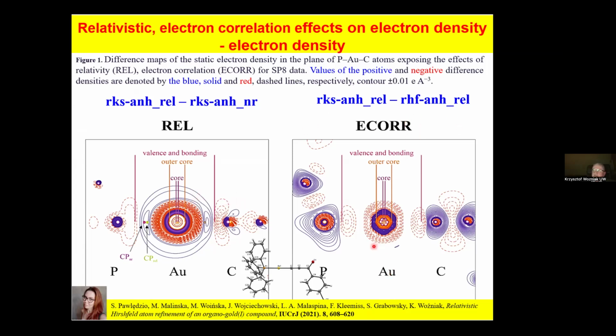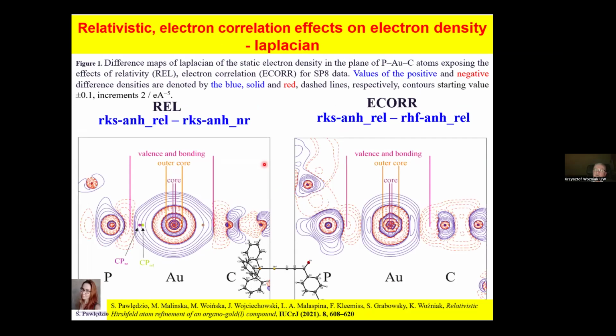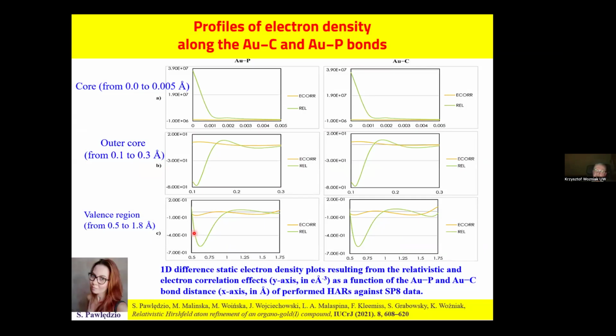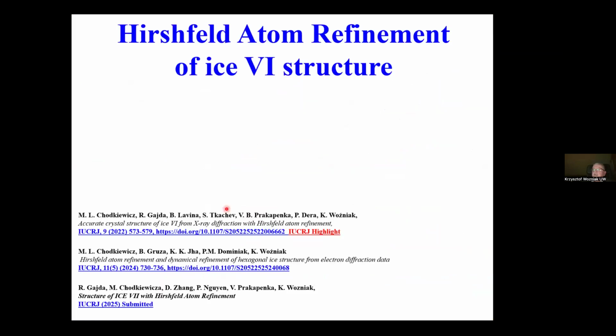In the case of electron correlation, we have electron density transfer to the neighboring atoms, and also localization of electron density close to the core electrons. And even more pronounced differences we can observe in Laplacian distributions. I do not want to go into details because we can see exactly the radial dependencies, how those two effects change. But if you are interested in details, you can go to those papers I mentioned at the beginning.